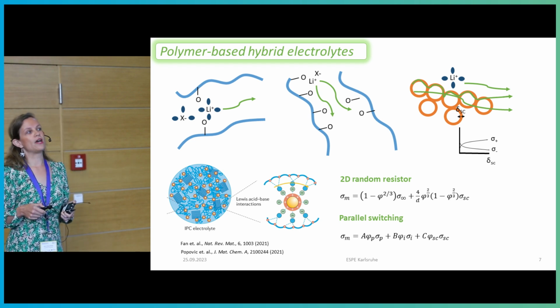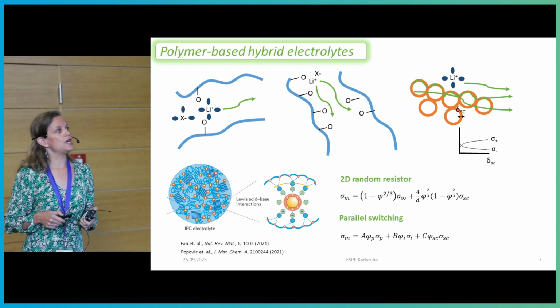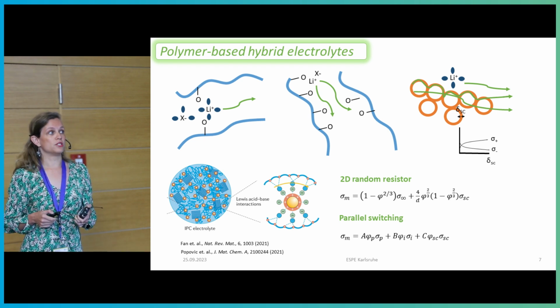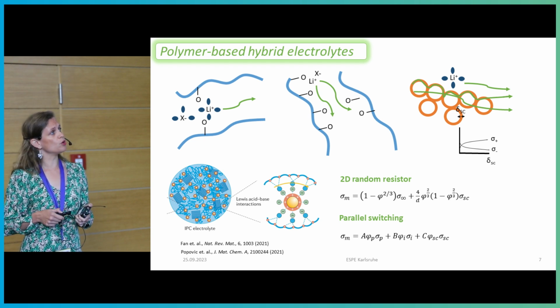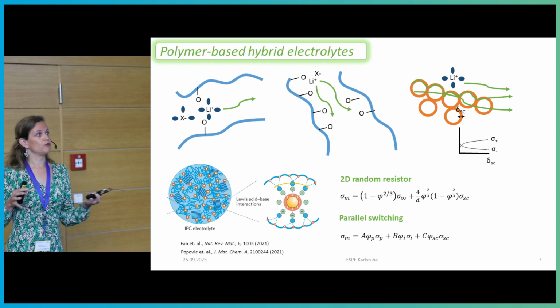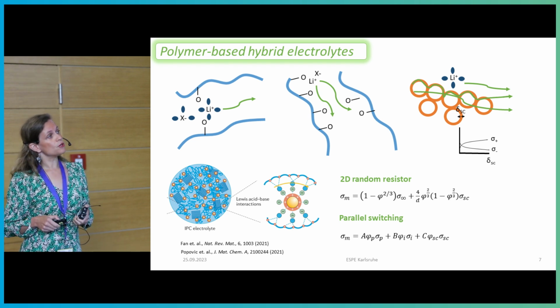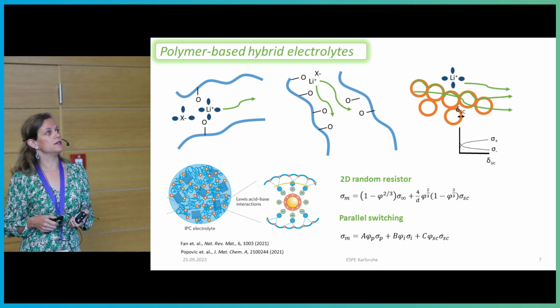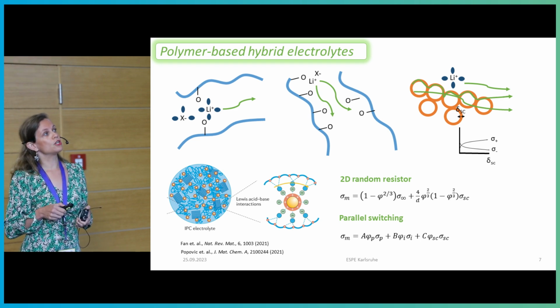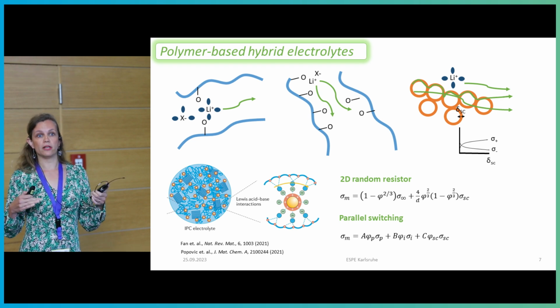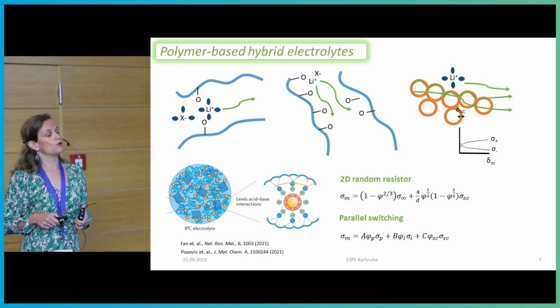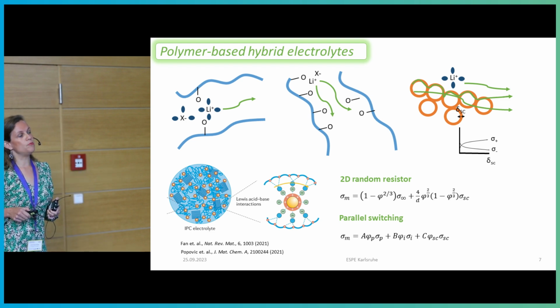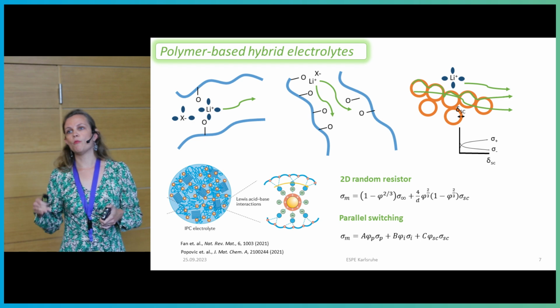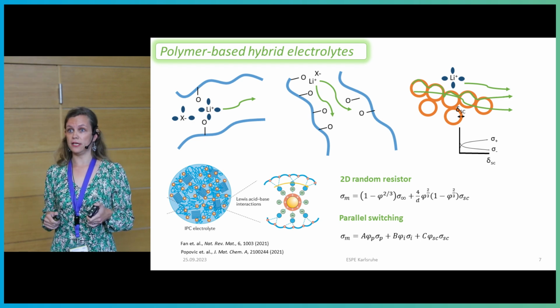One is the 2D random resistor model, for which we have to know the conductivity of the space charge zone, obviously, and the volume percent of the particles in the kind of resistor model. The other way that we have been using for many, many years is the parallel switching model, where we actually look at these pathways in parallel. And that means that we look at the conductivity of the polymer, of the bulk of the particles, and then finally of the space charge zones. And these A, B, and C parameters tell us how much of these pathways are percolating.